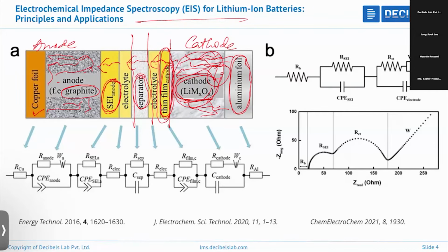So the electrolyte is a liquid medium. From solid to liquid, when it enters, there will be a change in the resistance, right? Then the lithium ion has to pass through that solid thin-film separator. Again, the resistance will be different. It may not be the same. So the rate at which the lithium ion moves is not constant. It changes from one stage to another. Then again it will enter the liquid electrolyte, then it has to pass through the solid electrolyte interface layer, and then it should intercalate into graphite.